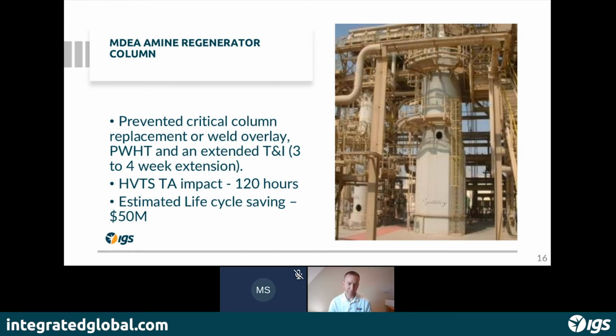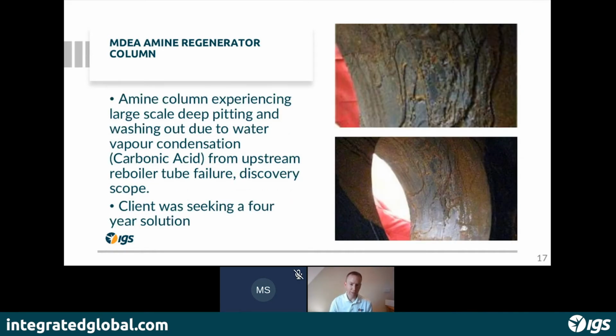What that would mean is having to stabilize the tower, having a crane, loosening obviously the flanges, the joints on the tower while they did the work, and also post-weld heat treatment. So that was going to potentially extend their shutdown by 3 to 4 weeks, which was unacceptable. So the IGS thermal spray solution was much more attractive to them from the perspective of keeping it within their original turnaround schedules. You can see from the pictures there some of the aggressive nature of the acid washout from the carbonic acid.